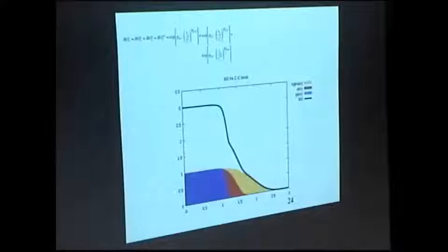And here we have an example of one specific parameterization for carbon-carbon, where I show how we calculate the bond order between these two carbons. Okay, we have this expression. Each term here is related to the sigma bond, pi bond, and double pi bond.